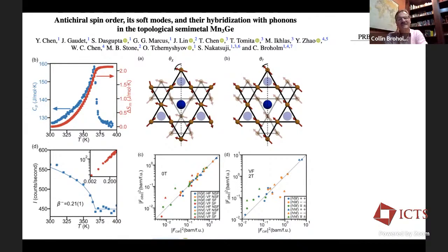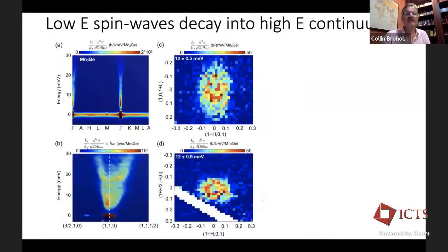So it's a very interesting kind of stealth ferromagnet, you could almost say. And so we've been doing full refinement of this structure. It's fairly difficult, in fact, to extract information about these structures from neutron diffraction, but with a high field and polarized beam, you can actually do it. We've also been looking at the magnetic excitations, and they look like spin waves at sufficiently low energies, and you can see some examples of that in these data.